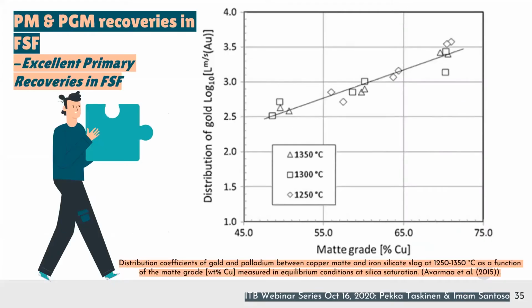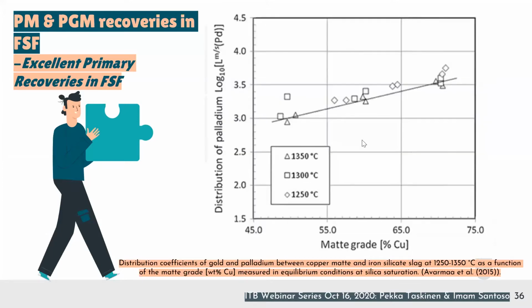So in case of gold, this distribution coefficient from those previous series of measurements at matte grades of 65 to 70% copper, they are over 1,000. So this is a logarithmic coefficient. They are from 2 to 3,000. And in case of palladium, even higher, so more than 4,000.